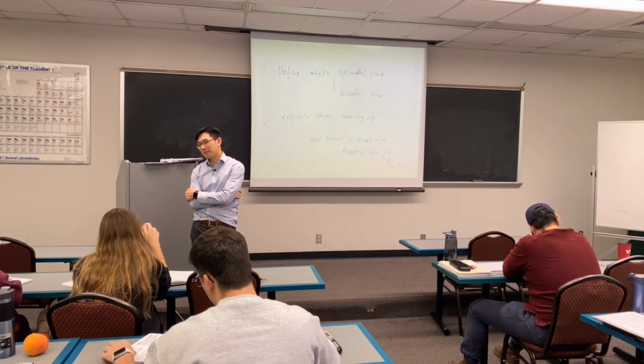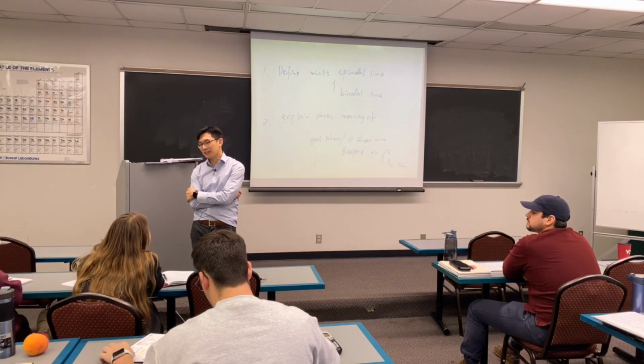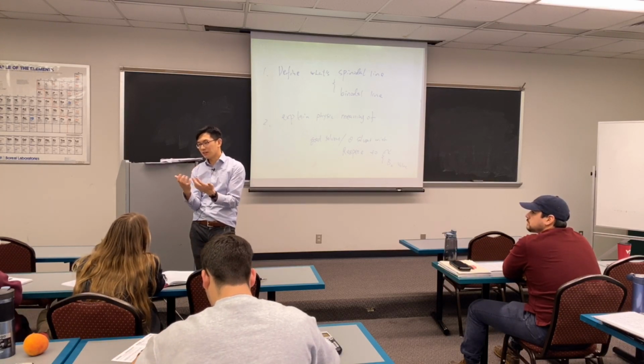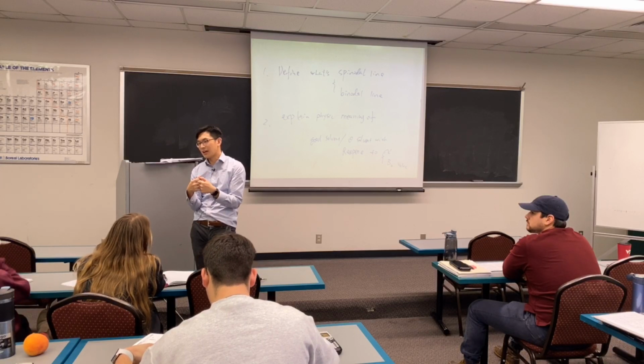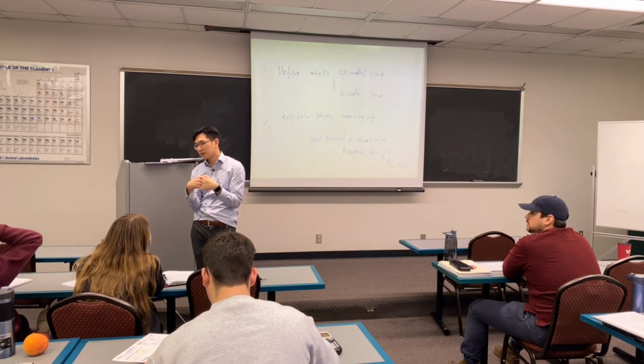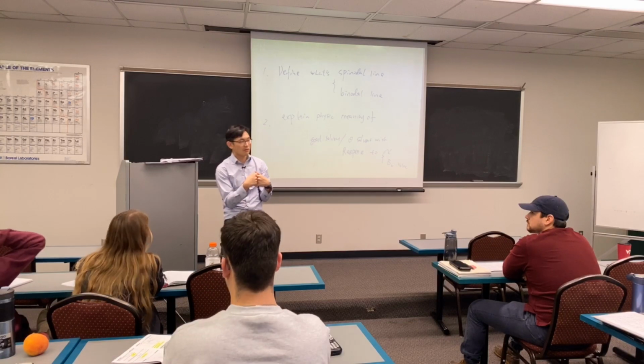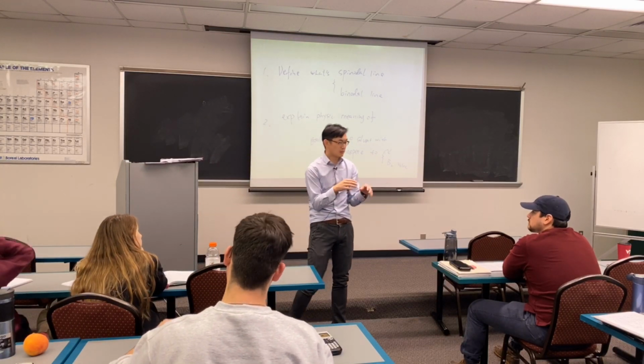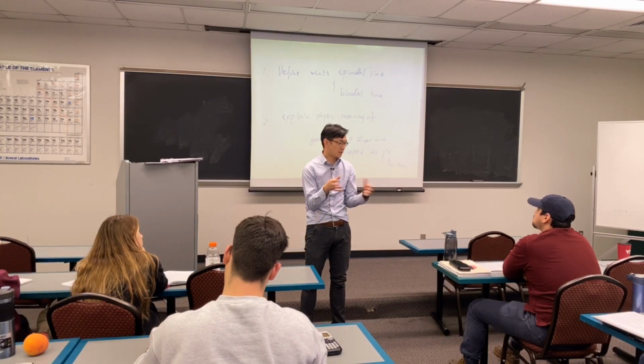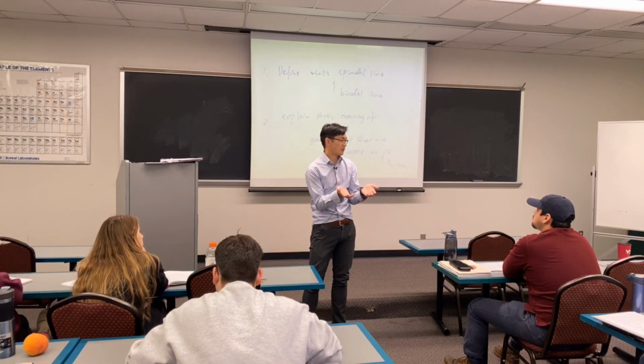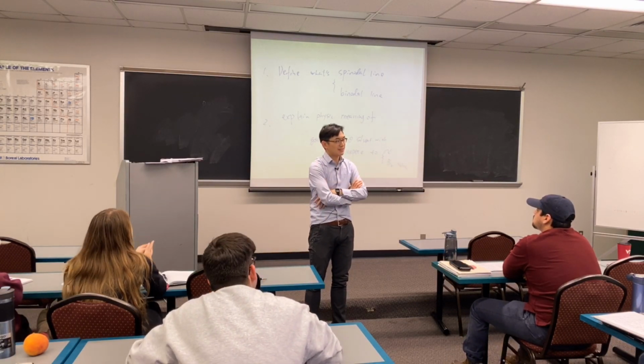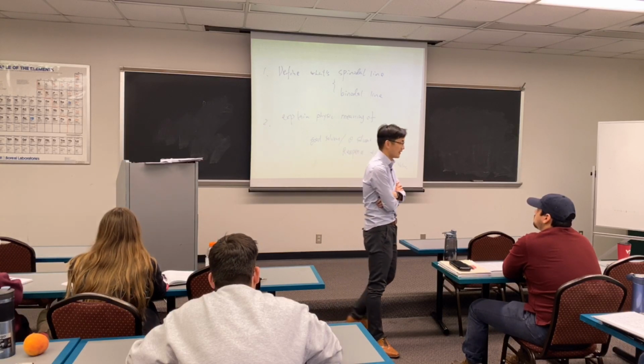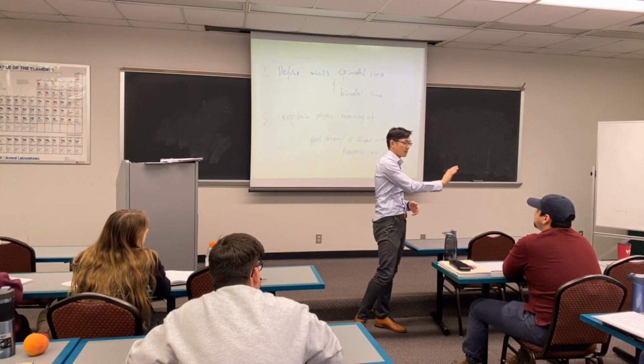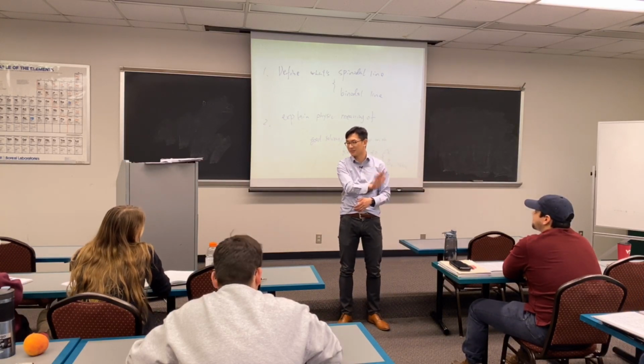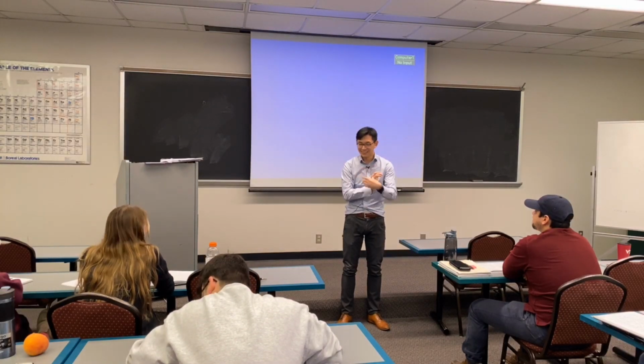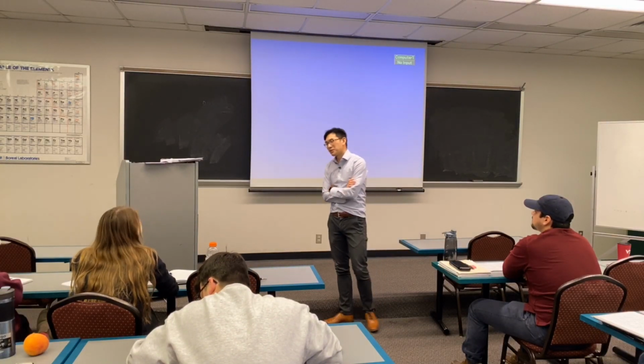But one of the caveats people find is that if you do not engineer the chi parameter properly, because you still have a driving force, a high chi, your material will phase separate at elevated temperature. If you put the solar cell outside, the surface can be as hot as 80, 90 degrees. Don't touch a black object in the summertime because it will burn you, right? It will start to phase separate.